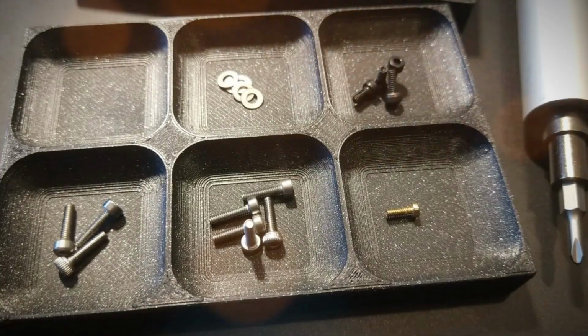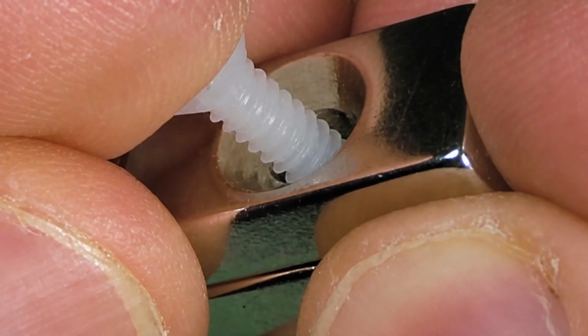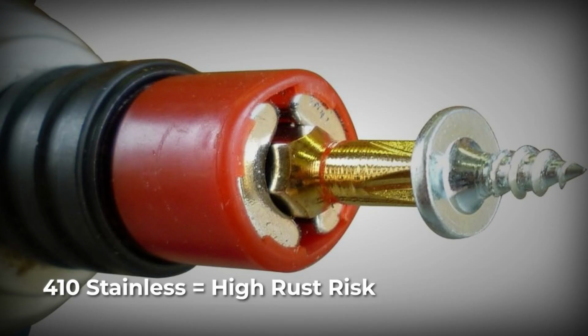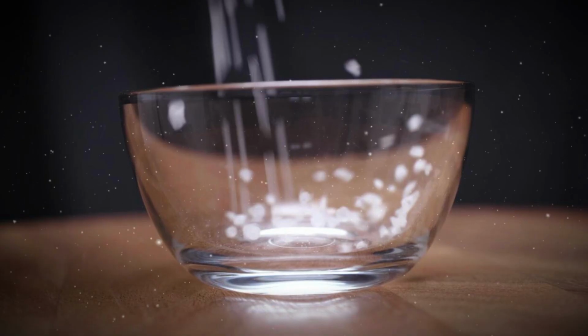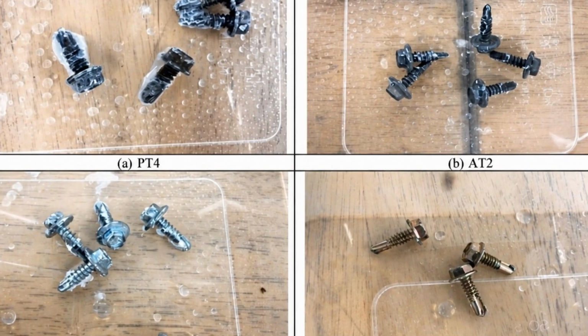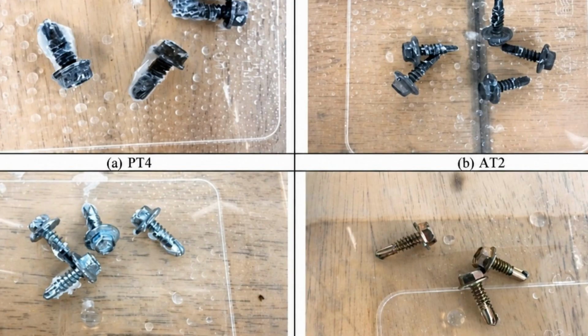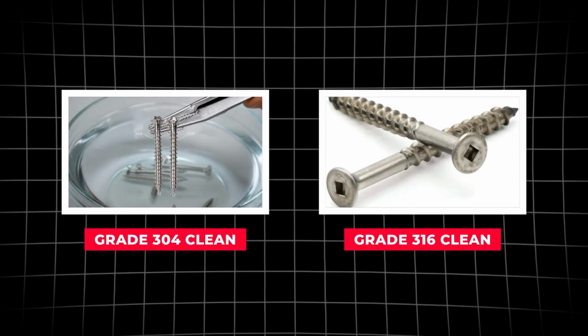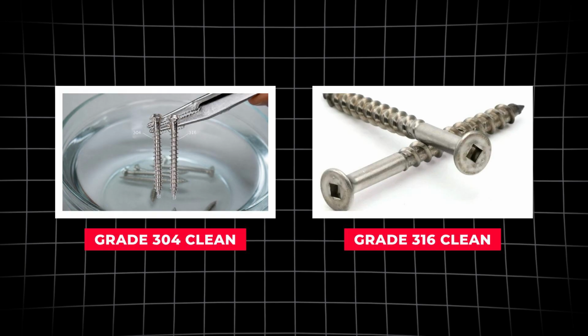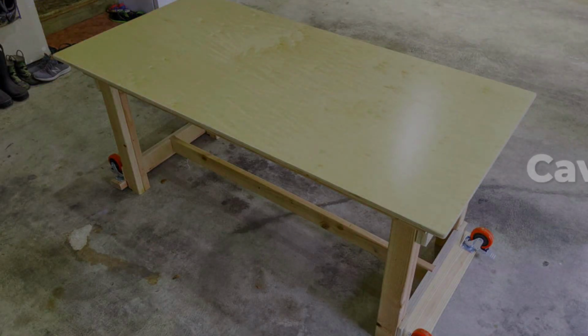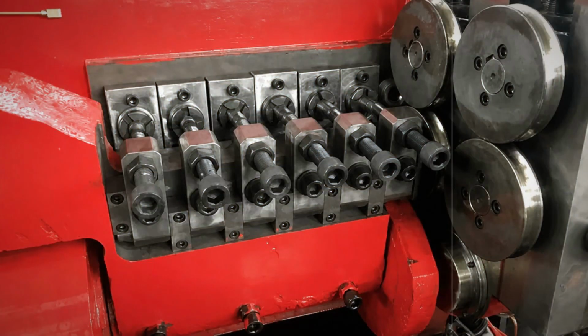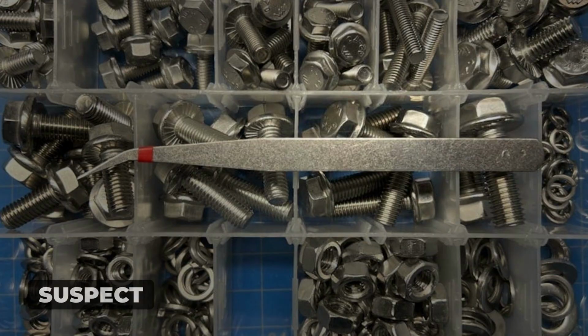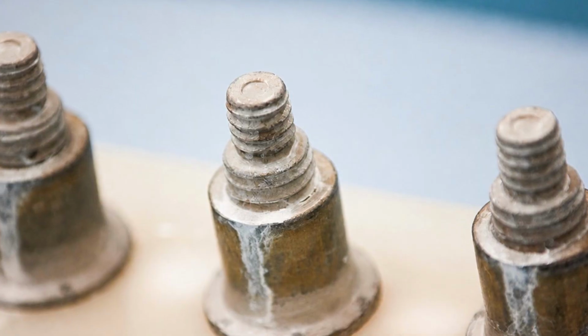Here's tonight's second test, and it costs nothing. Hold a magnet to the screw. If it sticks hard, it's likely 410, high rust risk. Then take a bowl, mix in salt, and drop a few screws in for 24 to 48 hours. Grade 304 and 316 come out clean. 410 starts spotting. One honest caveat, because it matters. Cold forming during manufacture can leave even genuine 304 screws mildly magnetic. So the magnet flags a suspect. The saltwater bowl convicts. Stainless is a promise the grade makes. The word alone promises nothing.